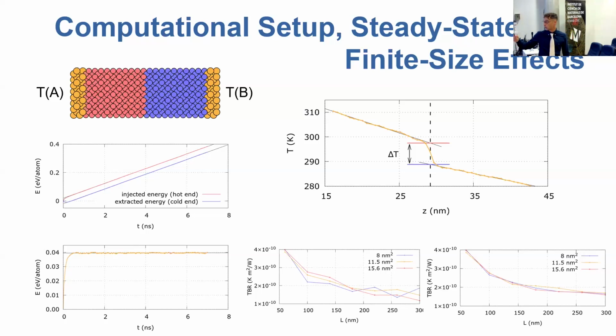We performed a total of 42 simulations to study the geometrical dependency of the TBR on the specific junction we were simulating. In particular, 21 simulations were performed at fixed temperature bias, meaning that TA was 350 Kelvin and TB was 250 Kelvin. And 21 more simulations were performed at fixed temperature gradient, meaning that the interface temperature was kept fixed around 300 Kelvin, but we increased TA and decreased TB in order to keep a constant temperature gradient across the system. In both cases, we can see that 8 nanometers squared cross-section was already enough to achieve a pretty fair degree of accuracy and convergence in our simulation.